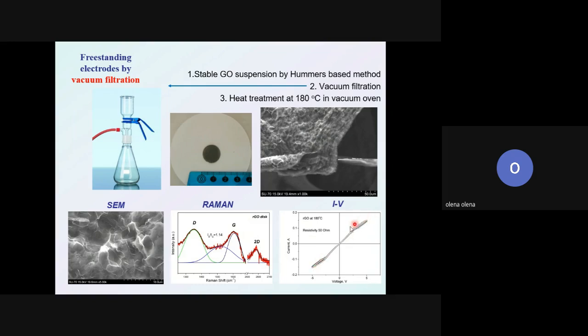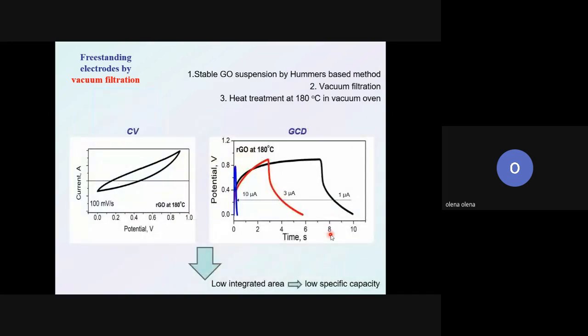We also studied IV, electrical conductivity, and you see we have very low resistivity of these materials. It means we have really reduced graphene oxide because, as I already said, graphene oxide is a dielectric and cannot be electrically conductive. However, when we studied electrochemistry, cyclic voltammogram for example, we see that our material didn't show the rectangular shape that we expect for capacitive materials, and the same for charge-discharge curves. So it's very fast charge and discharge. It means a small CV area, low capacitance, and we decided not to use it for the next study.